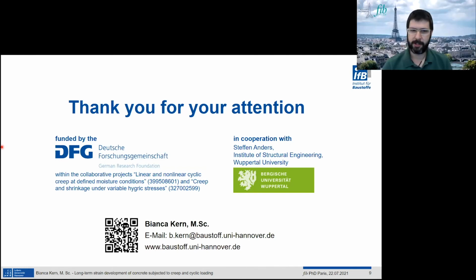And in this regard, how is the choice of the frequency for the study derived? Yeah, I chose very low frequencies. I also chose a frequency of 1 Hertz for further investigations because it's more realistic than higher frequencies. Higher frequencies also lead to an increase in temperature, which was presented yesterday by Martin Markert. Okay, thank you very much.